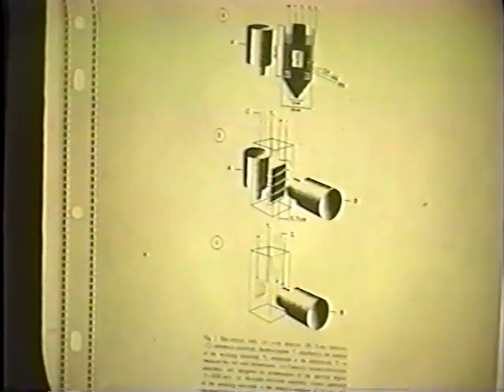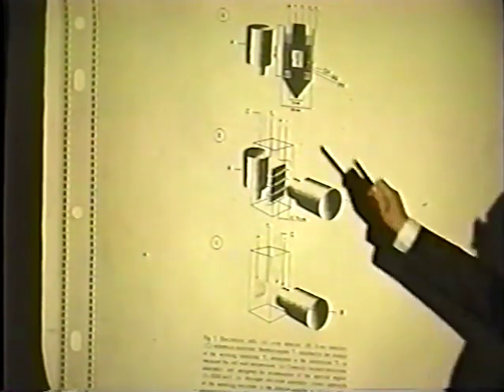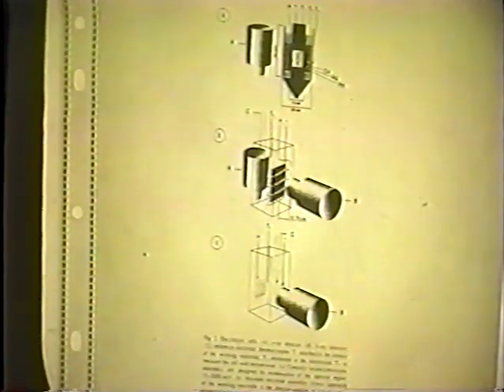In the first case, we were looking for only an overall picture. For that purpose, we use this arrangement here, which is very similar to the one which we use for the tritium analysis. And we use one detector, a high purity germanium detector. We set up to investigate the radiation between 15 and 3000 keV. That was the range which we looked at. And we noticed that there is some low increase, about perhaps 1 or 2% over that range. However, when we compress that range to about 15 to 300, we increase the excess to about 4%, which simply means that the radiation is rather toward the lower energy, not the higher.